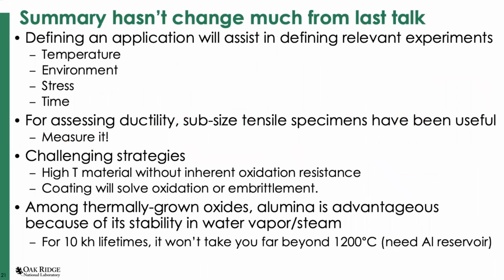So finally, I'd have to say my summary here is not going to change much from previous talks. I think that defining the application will assist in defining relevant experiments: temperature, environment, stress, time. And for things like assessing ductility, subsize tensile specimens have been very useful. And I think, again, if you want to talk about embrittlement, then measure it. There are some challenging strategies out there. Developing materials without oxidation resistance and thinking that coatings are going to solve the problems is a challenge. And then finally, among thermally grown oxides, alumina is always going to have an advantage.